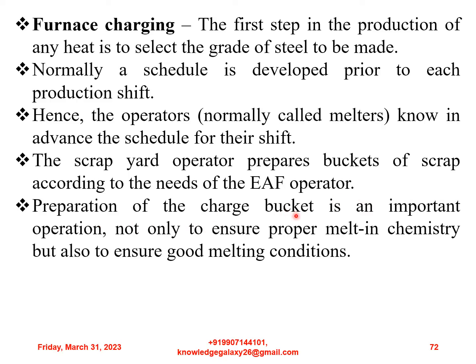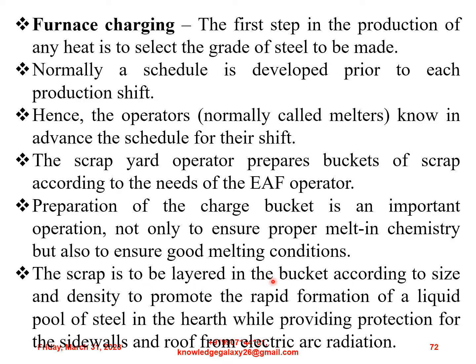Preparation of the charge bucket is an important operation not only to ensure proper melt-in chemistry but also to ensure good melting conditions. The scrap is to be layered in the bucket according to size and density to promote the rapid formation of a liquid pool of steel in the hearth while providing protection for the side walls and roof from electric arc radiations.